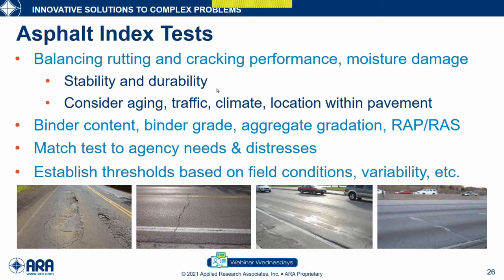There are many different tests for performance, and you want to match the test to your needs and the distresses that you see. There are four distresses shown in this slide. On the bottom left is a fatigue crack, second from the left is a thermal crack, then on an asphalt pavement, some rutting, and the one on the right is a reflection crack. So depending on your typical distress and what tests are best suited for it, you choose your performance test. And then you establish some thresholds based on field conditions, variability of the test, your experience, and practicality of the test.